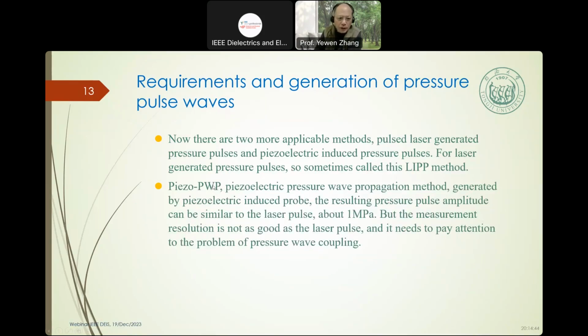Requirements and generation of pressure pulse waves. Now there are two applied methods: the laser generated pressure pulse and the piezoelectrically induced pulse. The laser generated pulse is sometimes also called LIPP. The PWP, piezoelectric pressure wave propagation method, is generally by a piezoelectric probe or generator. The resulting pressure is similar to laser, about 1 megapascal. But the measurement resolution is not as good as the laser.